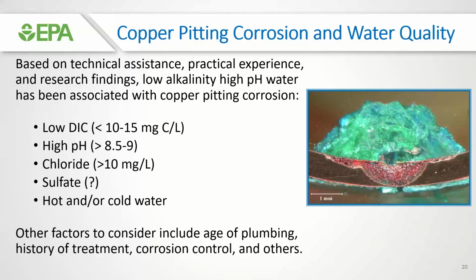So when do I see problems? Well, look, over the years, and I mean decades, I would say 80 to 90% of problems come about in the case of low DIC waters, that is 10 to 15 milligrams of carbon per liter, high pH 8.5 to 9, chloride concentrations greater than 10, maybe sulfate's important, hot and cold water could be either issue. But anyways, that's the magic water right there.